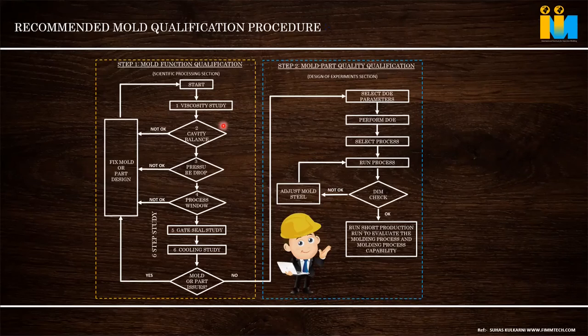How to derive it? If our mold is properly designed, with cooling lines close to the part and all the thumb rules followed, then how do we derive the correct cooling time? We have spoken about the heat distortion temperature of the raw material, the temperature at which the material gets distorted. The principle is that we have to eject the part from the mold below the HDT. It should not be too far below, or we are wasting cooling time. So it is 10 to 15 degrees below, safely.